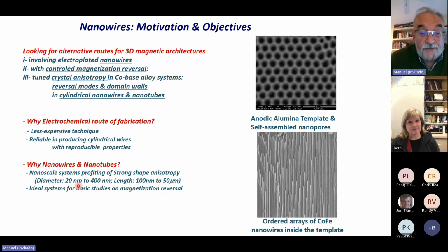And I can tell you the range of the dimensions. We can tailor the diameter from 20 to 400 nanometers and the length from 100 nanometers to 50 microns. So we can actually reach a very large aspect ratio, length to diameter.